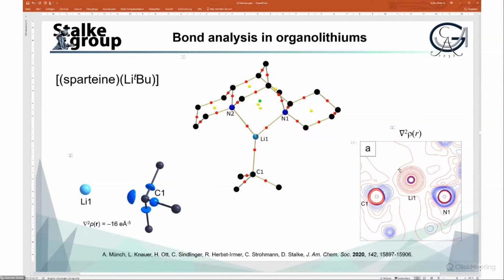Then we see a round, undisturbed lithium cation depleted by all the electron density, and then the VSCC pointing towards the lithium in the same fashion as the donor base does, as the electronegativity of nitrogen is higher than that of carbon, 2.55 for carbon and 3.04 for nitrogen. It's more contracted for the nitrogen.